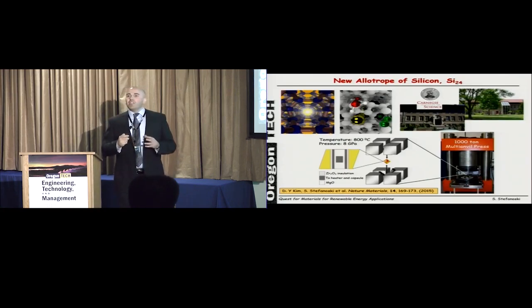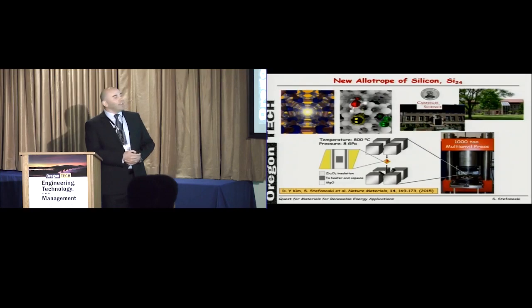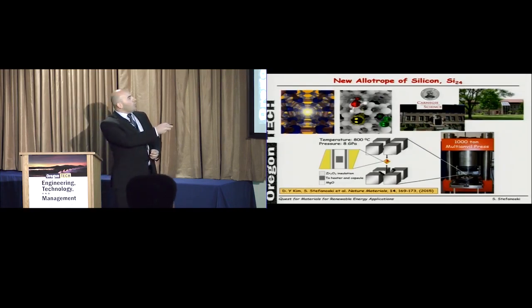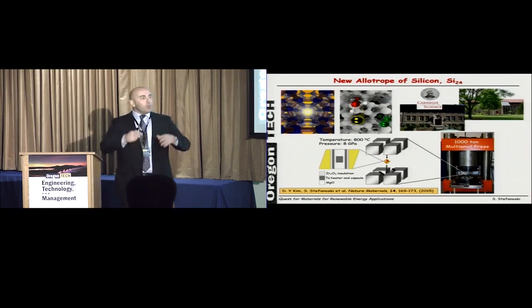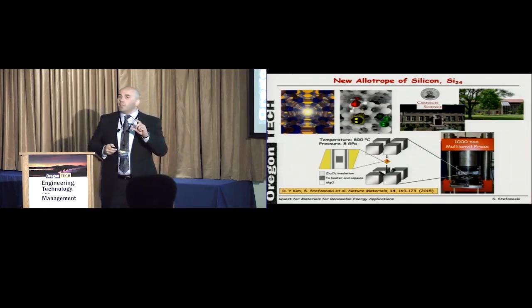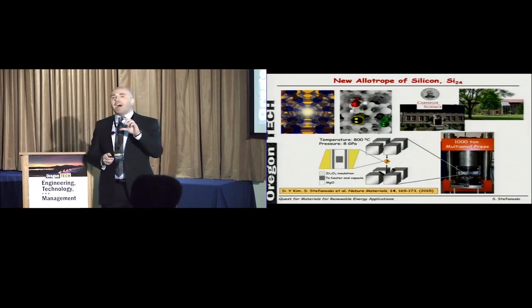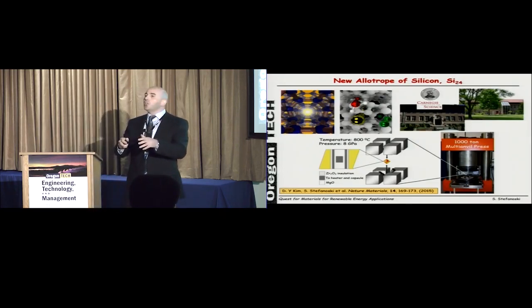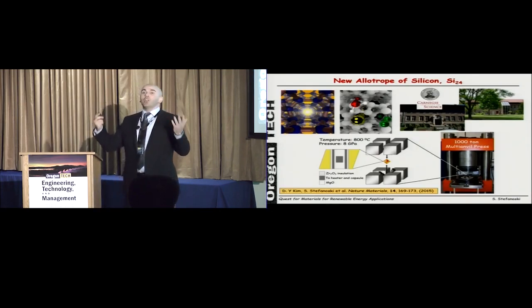The way we synthesized this material was applying a high pressure methodology with this multi-anvil press. Basically we started with a mixture of sodium and silicon in a 1:6 ratio, and we squeezed it at high pressure of about 8 GPa. This is a pressure which is about 35 times less than that in the center of the Earth, and brought it to a temperature of about 600 degrees, and we observed a miracle happening.